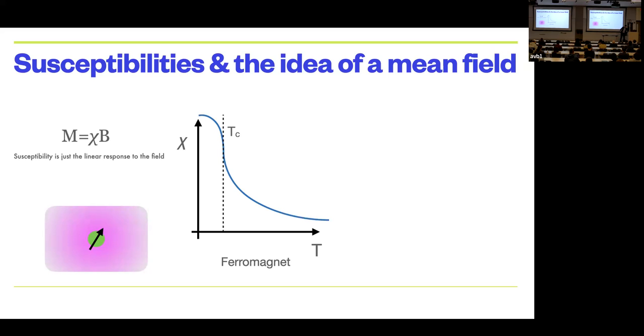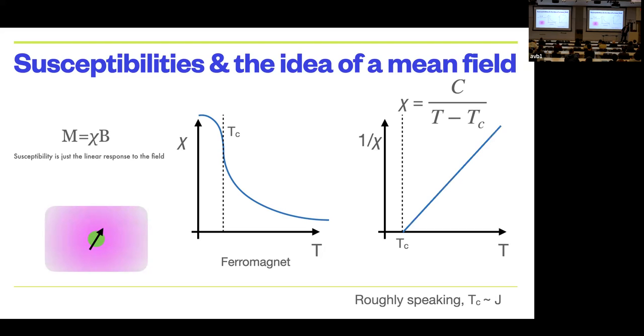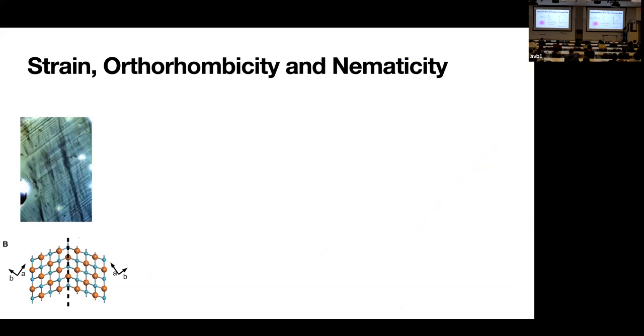Okay. So on the left I've got an equation which relates magnetization, the order parameter of a ferromagnet, and its response to an applied magnetic field, represented here as B. Chi is what we call the susceptibility. It's the linear response to that magnetic field. And as you're cooling the system in temperature, that linear response, chi, becomes larger and larger until it makes the transition into the ferromagnetic state. Now, we have a theory for describing susceptibilities. And that theory basically tells you that susceptibility is inversely proportional to temperature minus Tc. And that Tc, as I mentioned earlier, is basically a measure of the energetic strength of your interactions. Okay. All right.